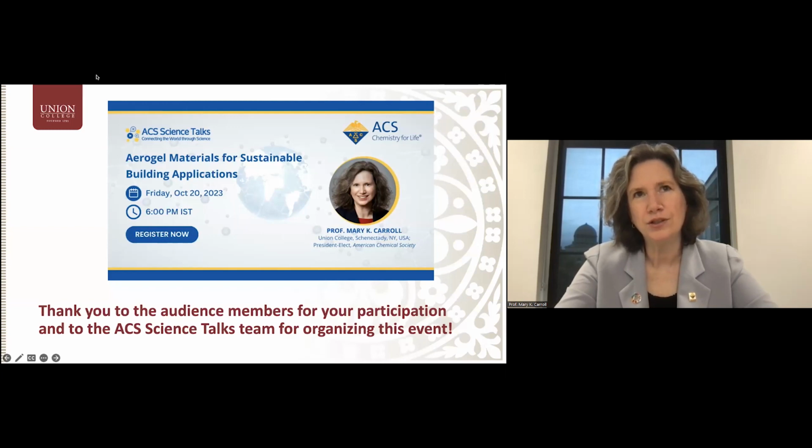The pressure, I don't have the number off the top of my head. The pressure is not that different from the CO2 pressure. It's the temperature that's a big difference. And so to take any of the alcohols supercritical, you need temperatures in the range of 260 to 280 degrees C, and that is hot.